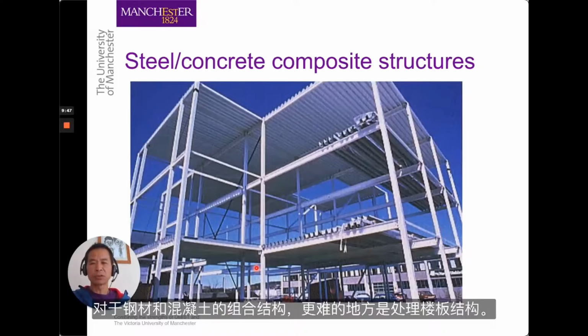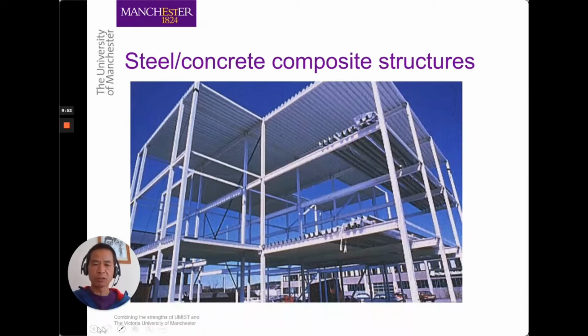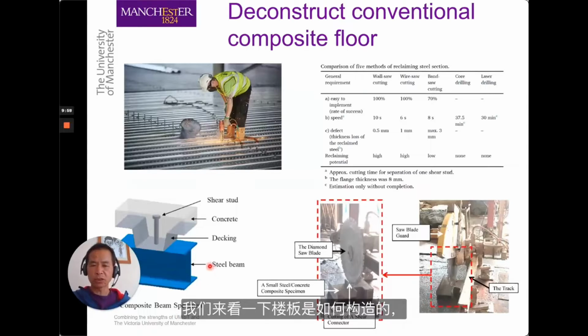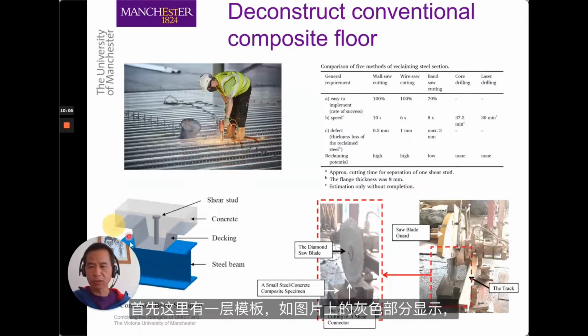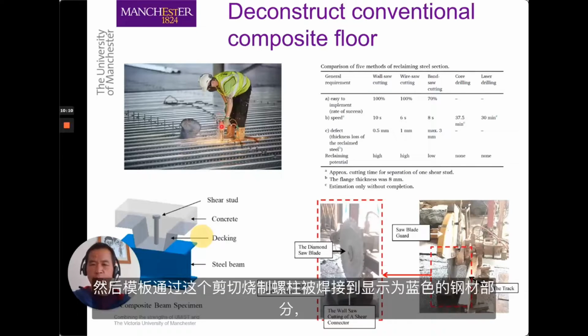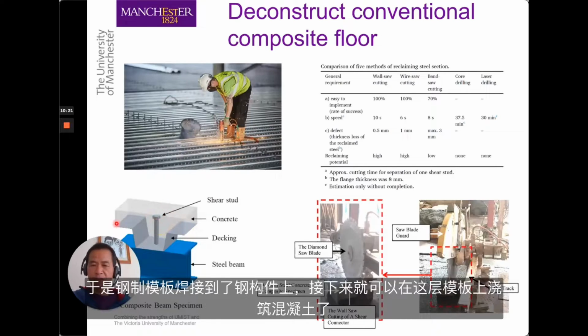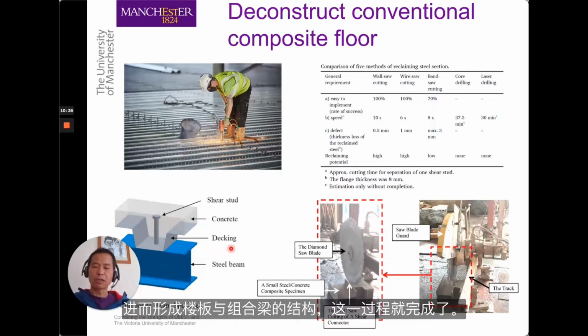For composite construction between steel and concrete, the difficulty is more in dealing with the floor construction. If we look at how the floor is constructed, we have a decking, which is shown here by this gray picture. The decking is welded to the steel section, which is this blue color in here, by using these shear studs. This is welded to the steel section to weld the steel decking to the steel section. On top of the steel decking, we can cast concrete to form the floor and the composite beam construction. That's how it's done currently.